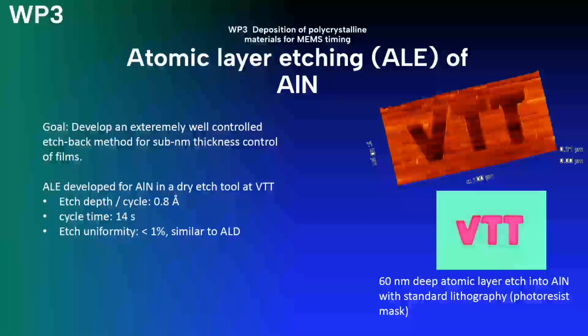Then in the polycrystalline materials work package, we are also working on etching. It's atomic layer etching, ALE, of aluminum nitride, where the goal is to develop an extremely well-controlled etching method, a kind of digital etching method for aluminum nitride. And we have established that in a dry etch tool at VTT, where we can do an etch depth of 0.8 angstroms per cycle, and the cycle time being 14 seconds at the moment. The uniformity of the etch over the wafer is better than 1%, so it's similar to ALD deposition uniformity. And there's some 60 nanometer etched recesses, the VTT logo. They're using the standard photoresist as mask.